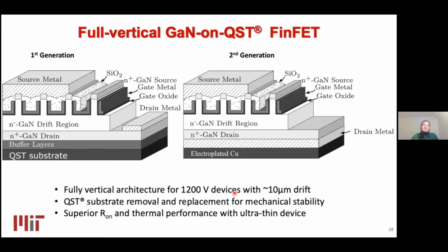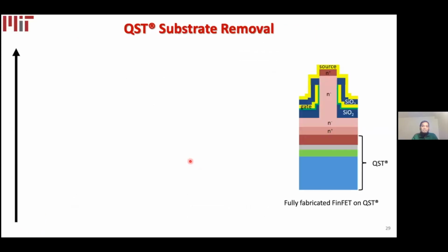If we want to achieve a 1200-volt rating, from our experience and calculation, we know that we need about 10 micrometer thick drift. To demonstrate this second generation device, we have to develop a substrate removal and replacement technology. We have to replace the substrate for mechanical stability. And since the substrate resistance was 75% of the total on-resistance of the FinFET, if we remove the substrate completely, it will also help with the on-resistance of the device and the thermal management, because of the ultra-thin nature and the conductive electroplated copper on the backside of the device.